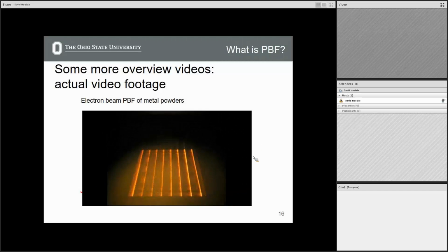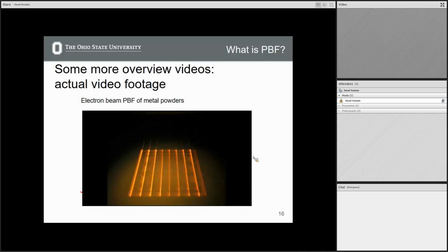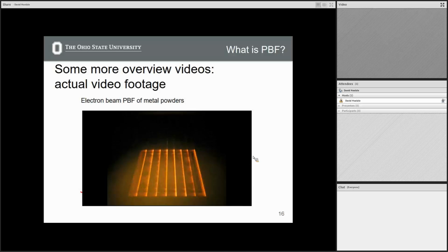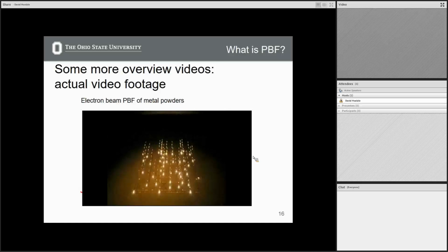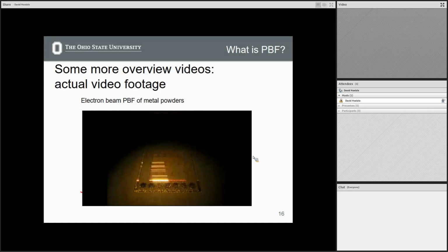Okay, so they're not actually building a part right now. What they're doing is a background heat of everything, and they're scanning. It's crazy, right? It's like some sort of EDM concert thing. So what you saw at the very beginning was essentially this background heating. Because they can scan the laser or the E-beam so fast, they're background heating everything. They're very lightly sintering that top surface, and they're keeping everything really hot.